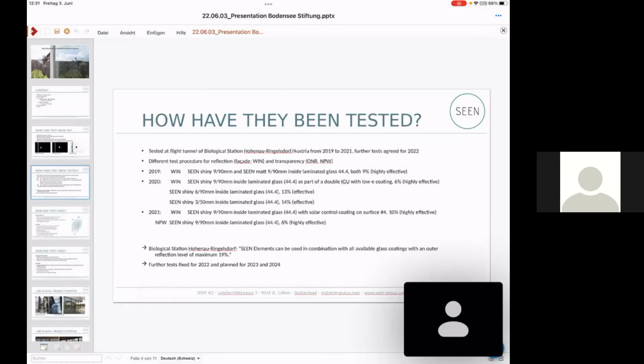Last year, we finally made, again, the 9/90mm pattern inside the laminated glass, but this time we used a more reflective solar control coating behind the dots on surface 4, and we still reached a highly effective result of 10%. The solar control coating had an outer reflection level of 19%, so it was really very reflective. And last year, we also started to test noise protection wall glass, which means SEEN Shiny on both sides. Again, in the 9/90mm pattern inside the laminated glass, and the result there was again 6%, highly effective.